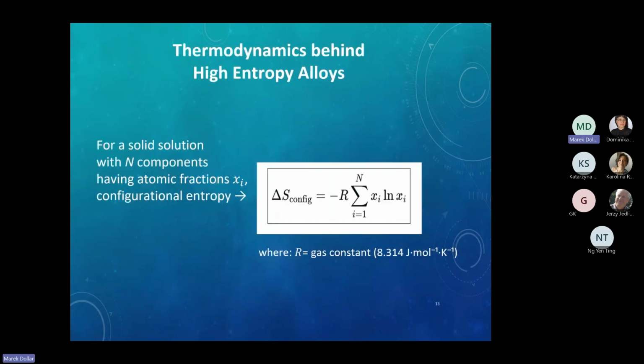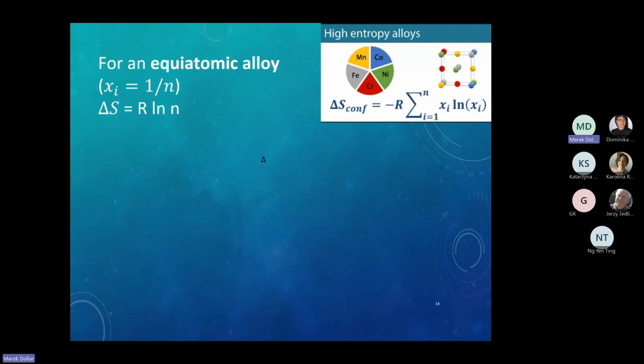Now, just 2 slides. Thermodynamics behind high entropy alloys. You have n components. In the Cantor alloy case, it is 5. All of them have sometimes different, sometimes the same atomic fractions. You calculate the configurational entropy, finding the products of the 2 terms, xi and ln xi, summing them up from 1 to n, multiplying by the universal gas constant with the sign minus. In an equiatomic, for example Cantor alloy, 20% of each element, xi equals 1 over n, which is 1/5. And you get the entropy of mixing from this simple equation.